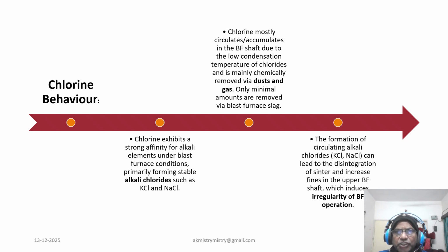Now this deposition within the burden, especially on the sinter, causes mechanical disintegration, which becomes a huge root cause of a number of abnormalities arising in the furnace.